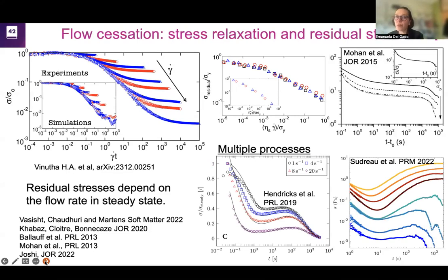But in fact, it's also very interesting then, as you explore more complex systems, it seems that this stress relaxation when you stop the flow can become even more complex. These are cases from recent experiments where people have seen, in fact, even non-monotonic stress relaxation. So the time scales that have been embedded in the system not only depend on the rate, but they seem to lead to development of structure at different time scales, which is maybe one mechanism that could lead to this non-monotonic stress relaxation that in fact has been seen, if I understand correctly, mainly in associating systems.